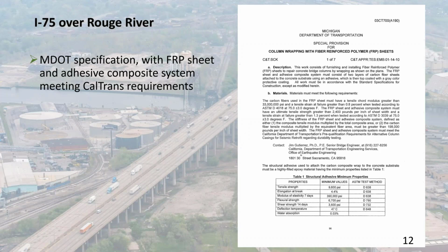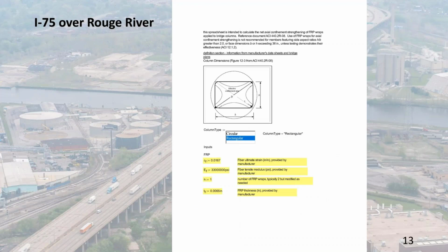We put together a MathCAD sheet, and ultimately we decided, so there are two main specifications we could have used here. We could have used the AASHTO guide specification, or we could have used ACI 440.2R-08. And ultimately, we decided to use ACI. Part of the reason is that the current AASHTO guide specification has a fixed FRP strain limit at the concrete FRP interface of 0.005. So you really don't get to mobilize more of what strain the materials are capable of. ACI allows FRP strains up to 0.009, depending on the concrete compressive strength, and it maxes out at an allowable concrete compressive strength of 8 KSI.